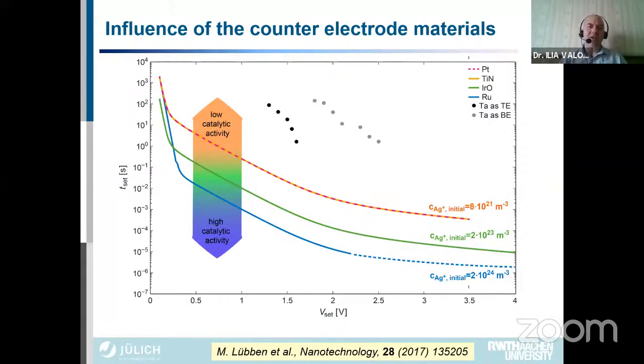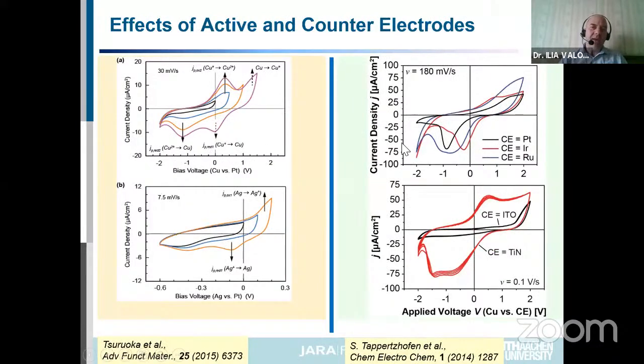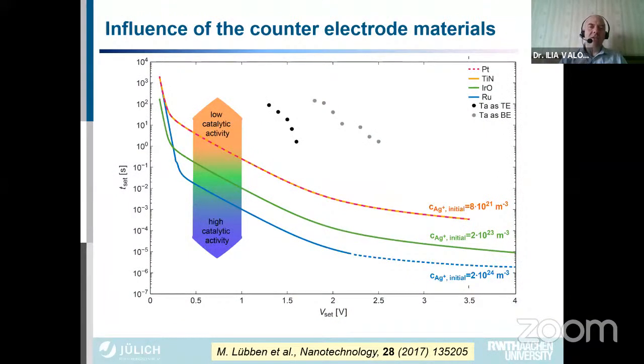And here you see the real operation. In the previous slide, you have seen only the electrochemical responses without switching, without complete function. And here you see the device kinetics, already switching kinetics, which means changing the resistance state with the purpose of either neuromorphic or memory functions. You see, the higher the catalytic activity of the counter electrode material, the higher the speed rate of switching. The lower is the time. And when you go to a lower catalytic activity, the time for reaction is much slower.